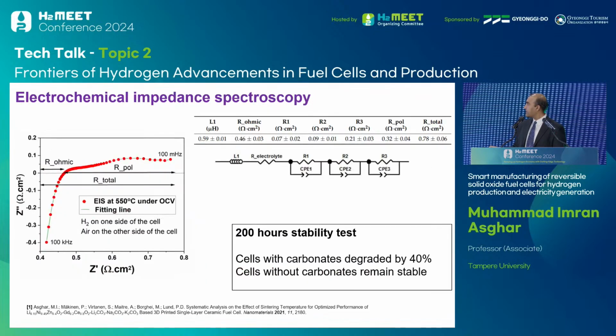So here's the electrochemical impedance spectroscopy data of our single layer cells. These cells suffer from high polarization losses, mainly because of low surface area. The cells are quite stable in the short-term stability testing that we have done for 200 hours. However, the cells suffer from these high polarization losses.